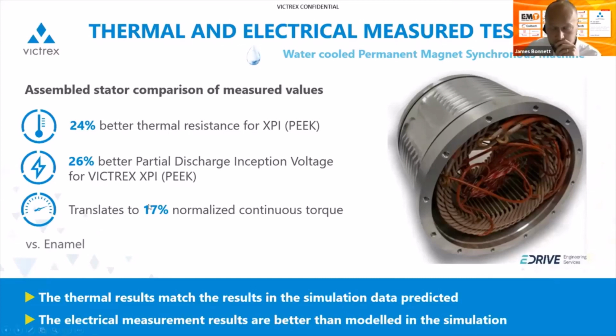The other important observation that we saw from this hardware testing was that the electrical measurement results were better than modeled in the simulation. In our simulation, we designed the electrical insulation system to basically have parity. So the enamel and stator and the enamel and the slot liner and the impregnation resin were designed to be the same as the thicker PEEK with a thinner slot liner and similar impregnation resin. And we've actually measured a 26% better partial discharge inception voltage value for those two different stators, which is very significant, but pleasantly surprising.